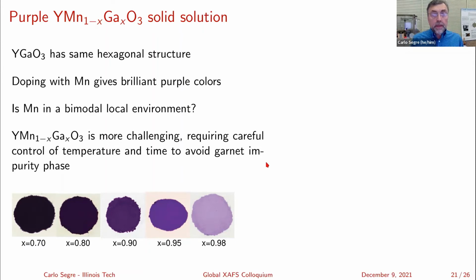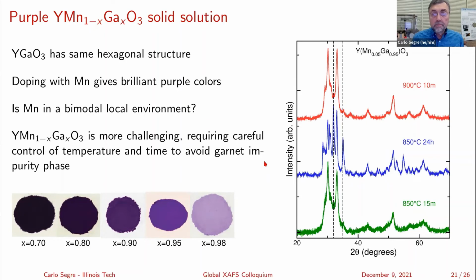The problem is it's much harder to make. It's the only one that we know that goes across the entire range, and that there are structures on either end that are identical. The problem is there's a garnet structure that builds up in between. And you can see over here, he was trying, when you're in the very dilute manganese and the high gallium content, we have to heat it for 15 minutes or else we get garnet. You can see right here, this is a big garnet peak. And if you heat it at 850 for 15 minutes, you're not seeing much of the garnet peak.